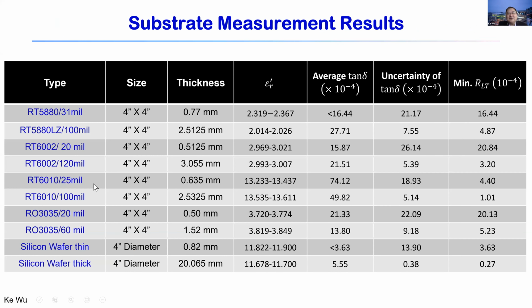And so this gives you different substrate measurement results. I will not go through the detail of that. All these results are based on a size of 4 by 4 inches, and the wafer is a 4-inch silicon wafer for thin substrates, and you can see thickness values here, and also the extracted parameter values, complex permittivity. This shows the real part and the imaginary part, which is in terms of loss tangent values here.